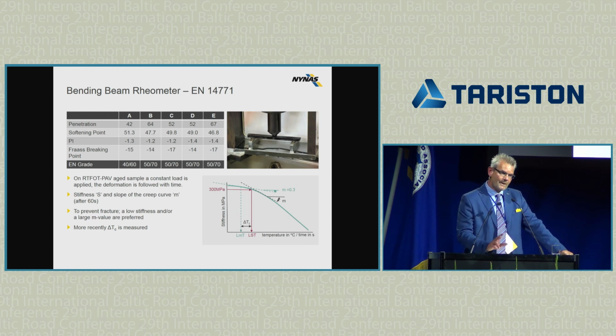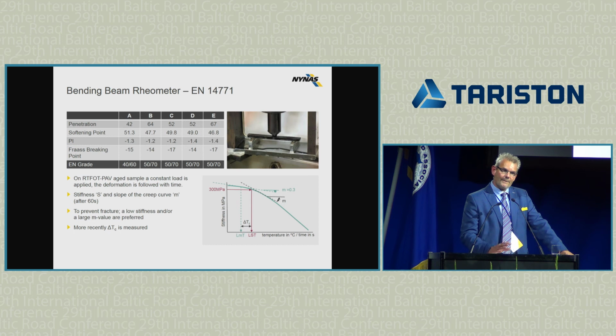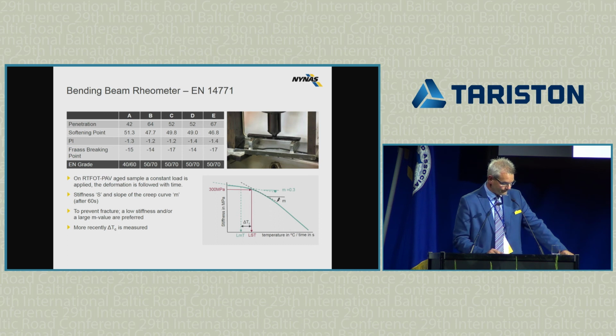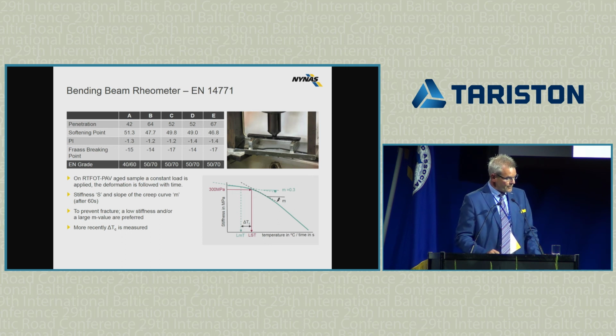In the bending beam test, you basically test 2 critical parameters. One parameter is called LMT, the limiting stiffness for relaxation, which is basically driven by the slope of the stiffness versus temperature curve. And the second parameter is LST, which is the limiting stiffness parameter. Now, these 2 parameters are an integral part of the Superpave specification. But what is new, and what they've discovered, is that this difference between these 2 parameters, delta TC, is quite important. It is this parameter that seems to be driving some of the durability failures on the asphalt pavement, and therefore it could be a parameter that says something about the durability of the bitumen.